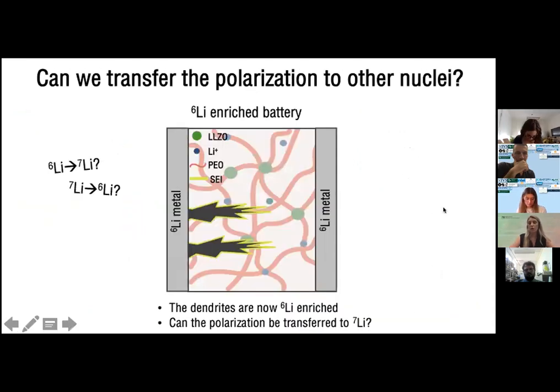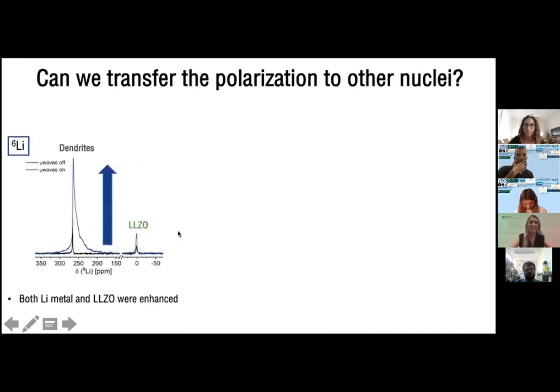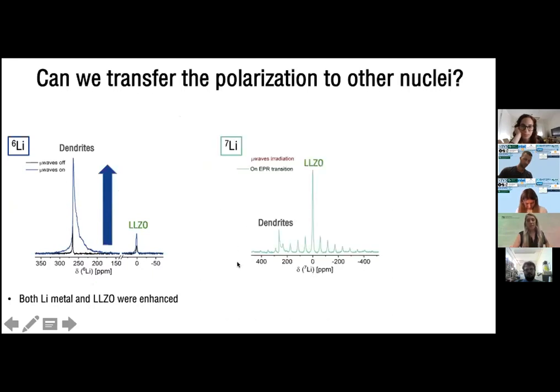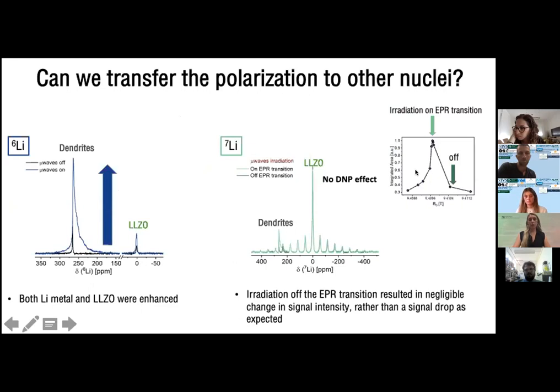The next question: can we transfer polarization to other nuclei? For example, phases with different nuclei of the composite, protons, carbons. So with that, we use this model system. We enrich our battery with lithium 6, use lithium 6 metal. So now our dendrites are enriched with lithium 6, mostly lithium 6. So you can see here, with microwave on, we have enhancement of the metal and the LLZO, as we saw. And now if we look at lithium 7, you can see here, this is exactly radiation on the EPR transition. And if we go off that,